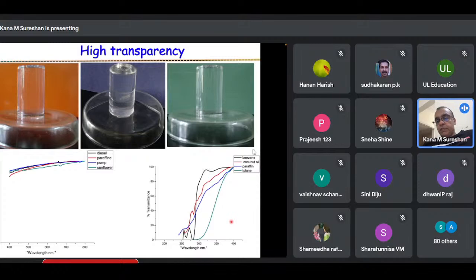But in the UV, from 400 to 200, there is a complete absorption. So from 400, it is going to zero, actually. That means no transmittance, or this UV light is not being transmitted to the other side of the jelly material. So that's very good. That means this gel can be used to filter UV out. UV is bad, of course, you know. That's why we don't look at the sun, for example, during an eclipse or otherwise. So this is possibly a filter which can filter out the unwanted UV radiation.